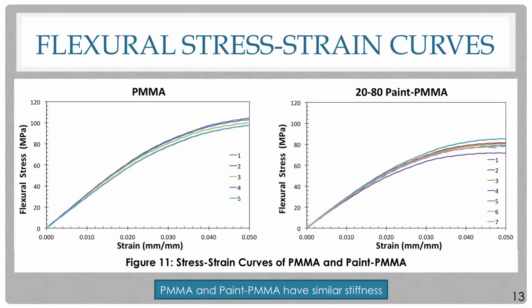After collecting and analyzing our results, we were able to generate a stress strain curve for each sample. According to ASTM standards, at least 5 specimens must be tested for flexural testing. For our paint PMMA sample, however, we tested 7 specimens to verify our results because 2 specimens broke as a result of contaminants found in the paint.